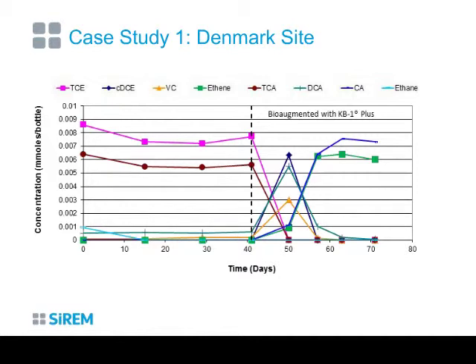And you can see for the first 40 days of incubation, where it was incubated with an emulsified vegetable oil under anaerobic conditions, not much happened. We didn't really see anything move at all. So at day 41, we bioaugmented, and what we saw was rapid and complete dechlorination of the 1,1,1-TCA to chloroethane and the TCE to ethene, which is very typical for the bioaugmentation cultures that we have available. And it also shows really nicely the dechlorination sequence. So you see TCE in pink going to cis-DCE in the dark blue, going to vinyl chloride in the orange, and then ultimately to ethene.